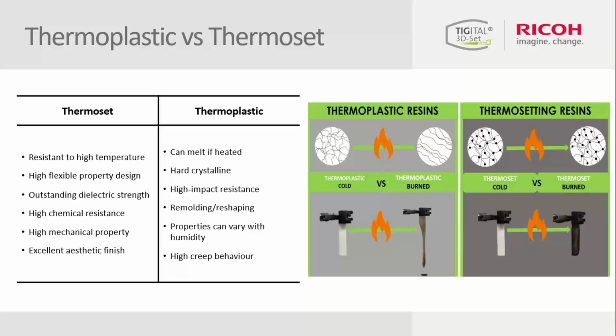Nobody needs this kind of material parts, but it's able to print with shrinkage below 0.5% in the printer. And because of the cross-linking of the Thermoset materials, we are reaching also high outstanding dielectric strengths. And the chemical resistance of Thermoset materials is in the polymer sector really common and used. That's why also for electrical application, because the Thermoset materials are not absorbing water-based systems or any solvents or liquid